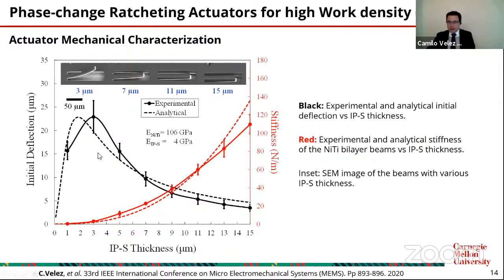And this was only possible because, by 3D printing, you can have only one wafer with the same nickel titanium pattern, and then 3D print on top of that multiple configurations of different thicknesses of the passive layer. This was amazing because it speeds up the process incredibly. You have a very robust actuator at the end, and it is a 3D printed actuator. So for prototyping, it's amazing. It's a very robust technique that you can leverage for designing your actuators in the future.